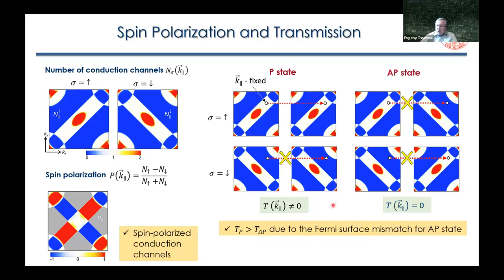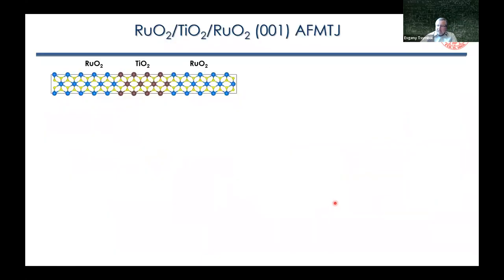Now let's make this more quantitative. So let's consider a specific example. This example is an antiferromagnetic tunnel junction based on ruthenium oxide electrodes. We are using titanium dioxide as a barrier layer in this system. Titanium dioxide is rutile, so it has the same structure as ruthenium oxide. Moreover, the lattice constant matches beautifully.